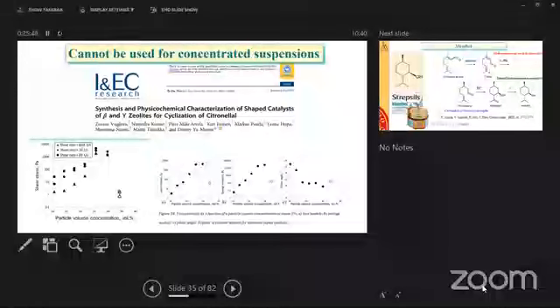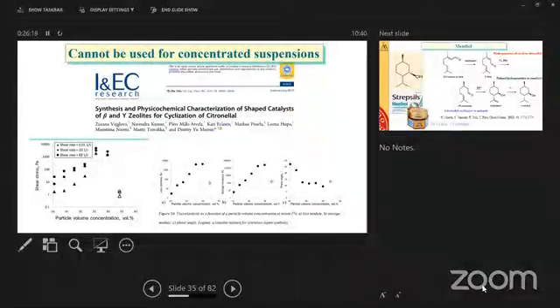The concentration of the solid can be 40, 45, 50%. And these rheological measurements and even the theories which are behind these measurements, they correspond to the solid content maybe 15, 20%. So we started to measure, for example, shear stress as a function of the particle volume concentration, and this is something relevant for us, 35%. Then these linear expressions, which I mentioned before, they're not valid anymore.